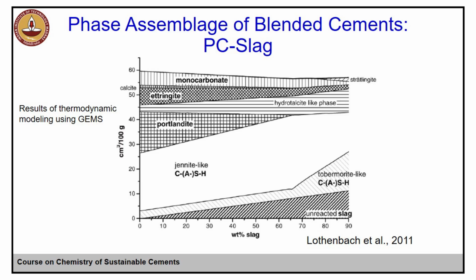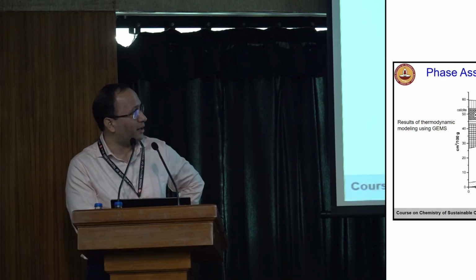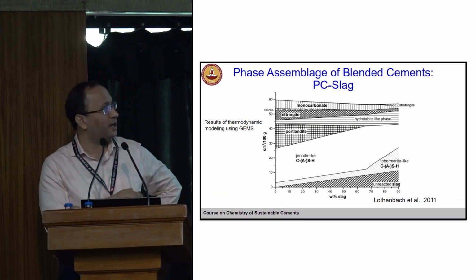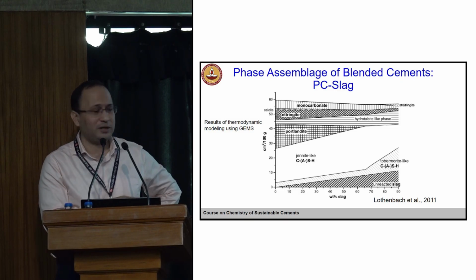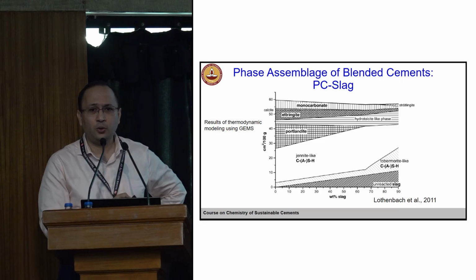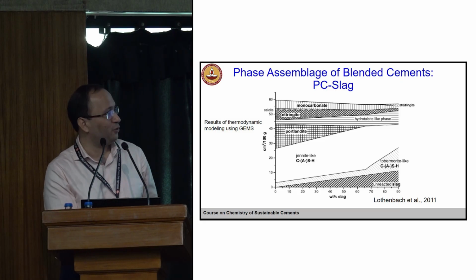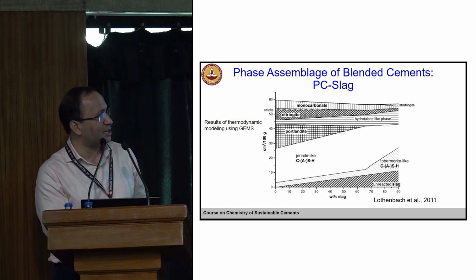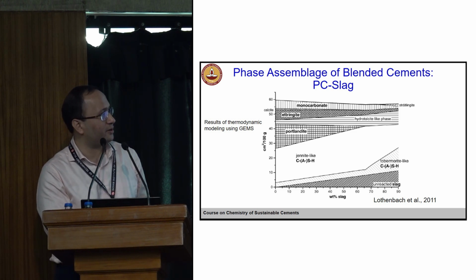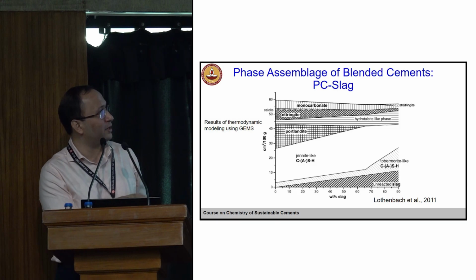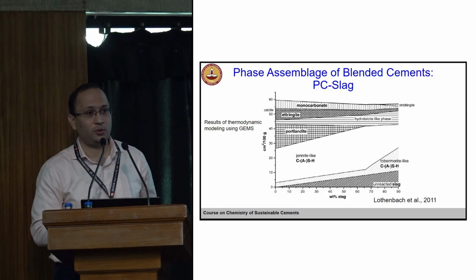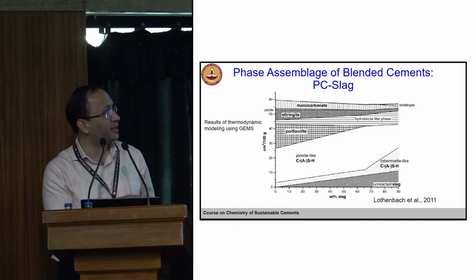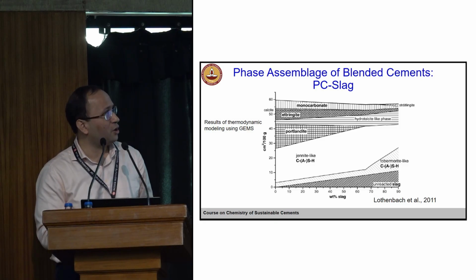Slag is interesting. It has some calcium in it. So the kind of changes you have seen in case of fly ash will be here also eventually. You will form low calcium to silicon ratio CSH, but it will take some time. You need more slag for that. So you have high calcium to silicon ratio CSH, then low calcium to silicon ratio CSH. It takes longer, you need more slag to fully consume, let's say, portlandite. But you have an additional phase like hydrotalcite, because of the magnesium and aluminum it brings. So chemistry and phase assemblage change a little when you have slag in the system.